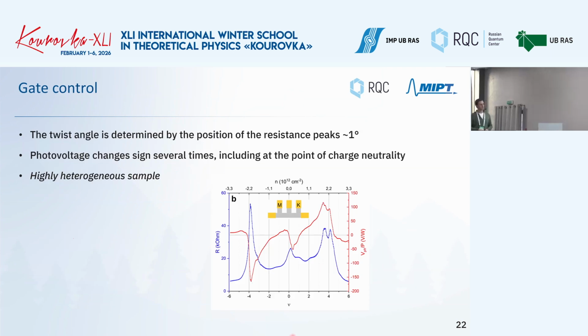This is an important image. For example, we have this in the cryostat, and we can measure the resistance depending on the gating. When we change the gate voltage, we change the carrier density, and then we can get to different fillings. Around 0 is called the charge neutrality point, and there are some specific increases of the resistance at the fillings of the moiré potential.